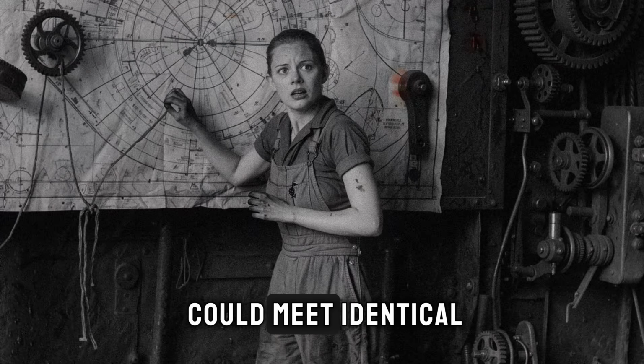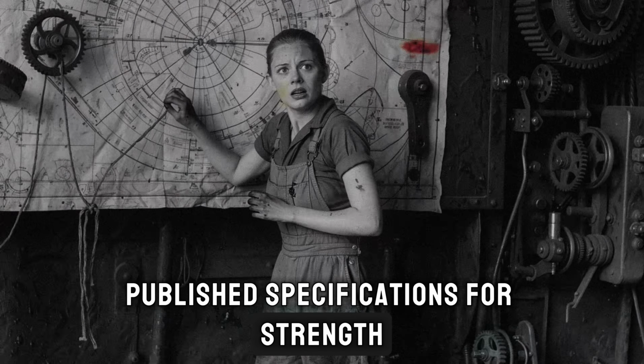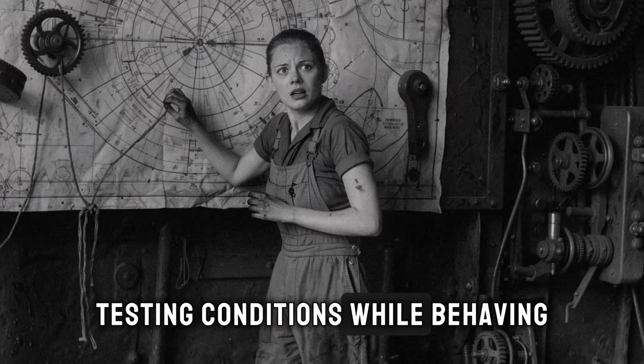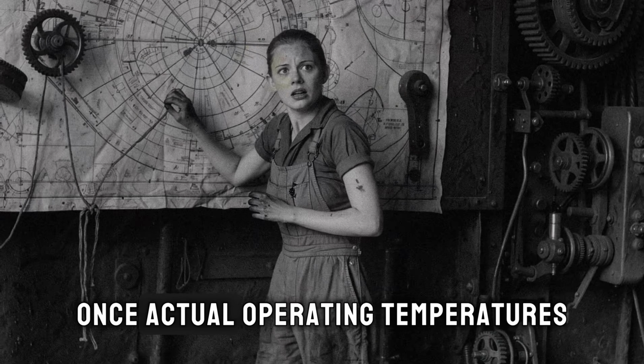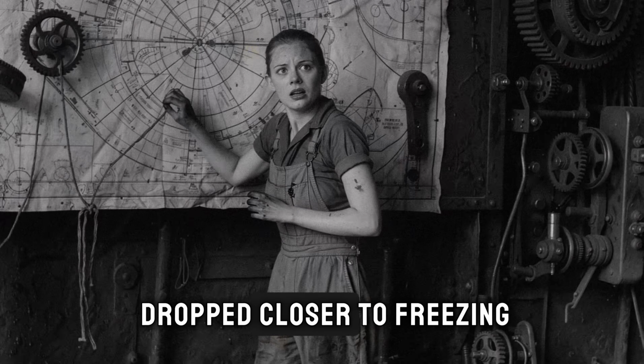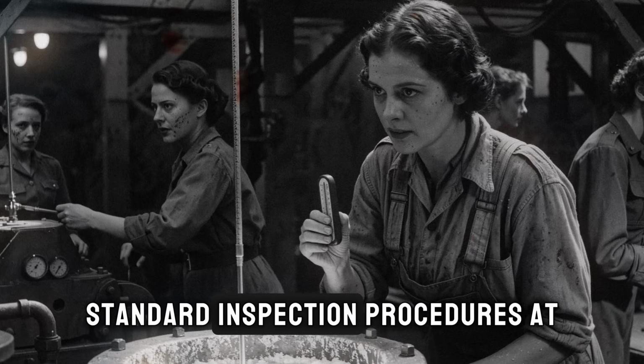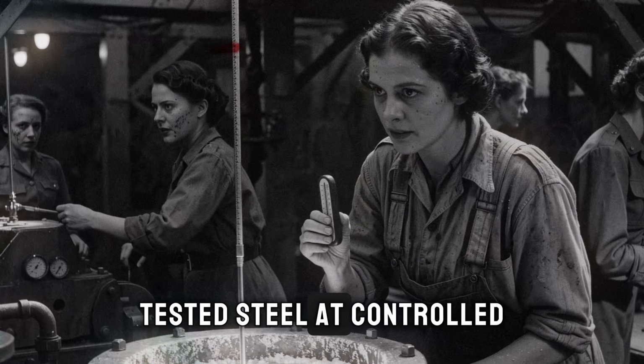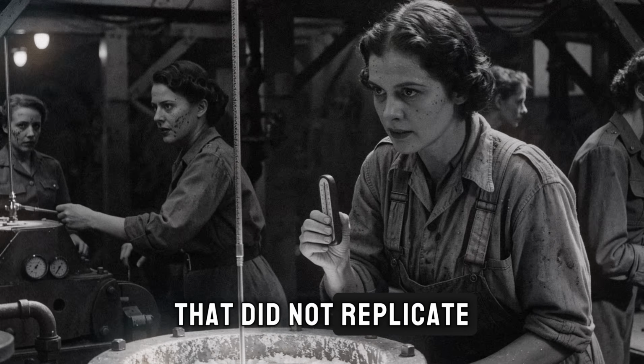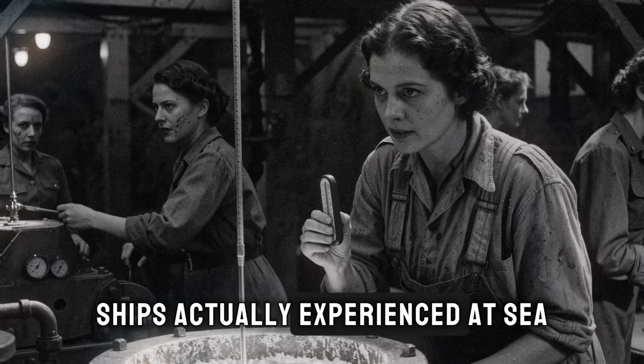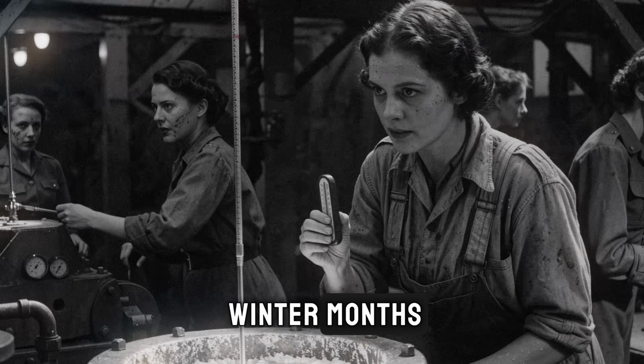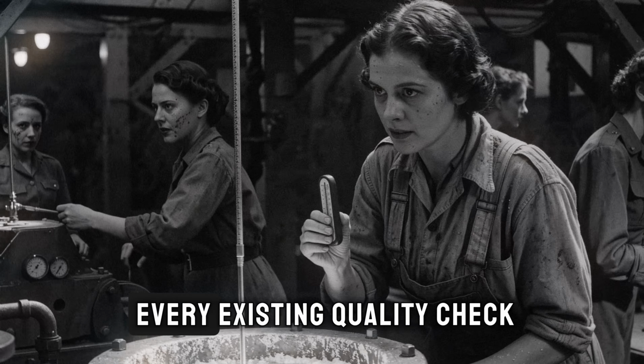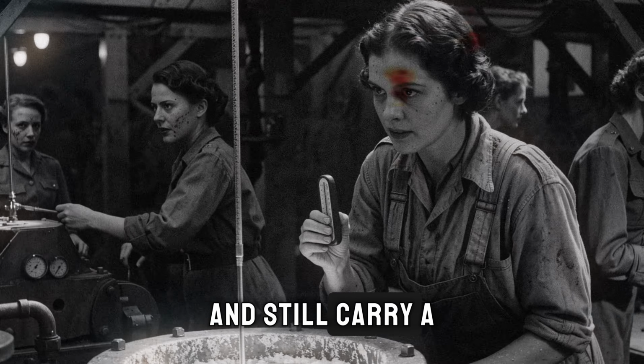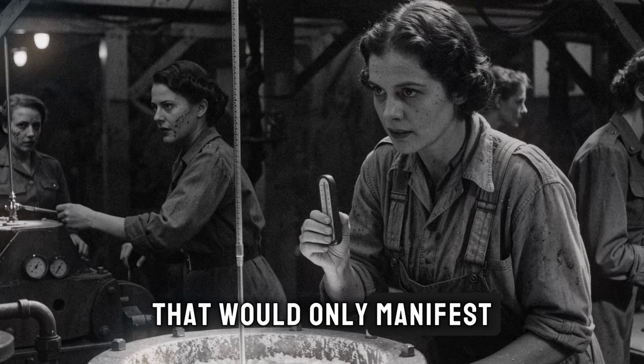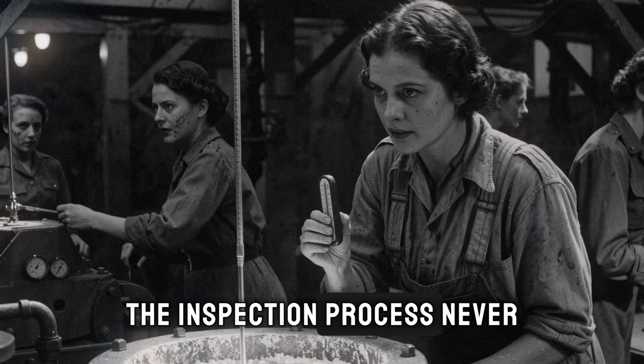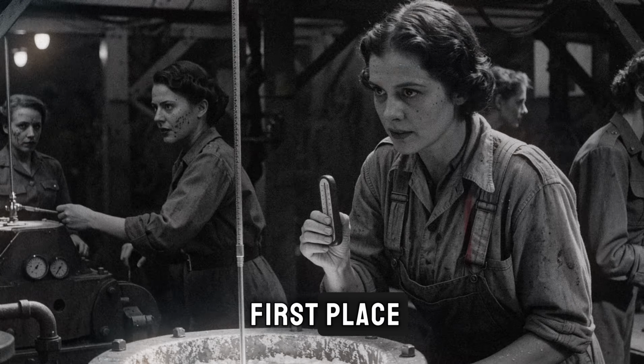Two batches of steel could meet identical published specifications for strength at room temperature testing conditions while behaving completely differently once actual operating temperatures dropped closer to freezing. Standard inspection procedures at the time tested steel at controlled laboratory temperatures that did not replicate the cold conditions ships actually experienced at sea or at dock during winter months, meaning steel could pass every existing quality check and still carry a hidden vulnerability that would only manifest under conditions the inspection process never tested for in the first place.